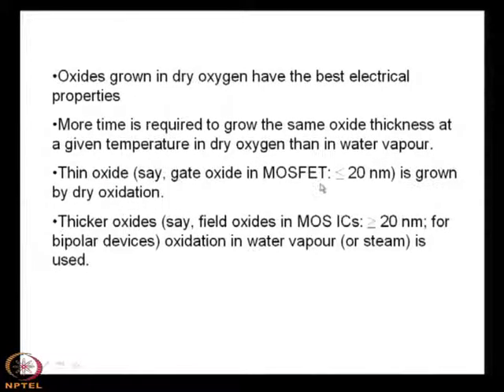Thin oxide means gate oxide in MOSFET, whose value is less than or equal to 20 nanometer, or thicker oxides, say field oxides in MOS integrated circuits, it is greater than 20 nanometer. For bipolar devices where the thicker oxides are required, oxidation in water vapor or steam is used. So, the factor that must be considered for growing the thin oxide or the thicker oxide is the thickness of the oxide layer. If it is less than 20 nanometer, one should go for the thin oxide, or if it is greater than or equal to 20 nanometer, one should go for the thicker oxides, and thicker oxides are grown using water vapor.